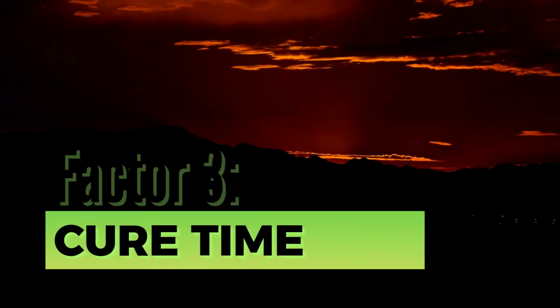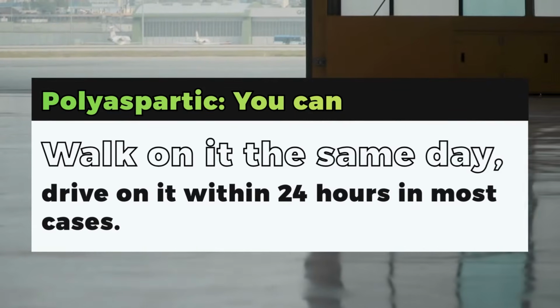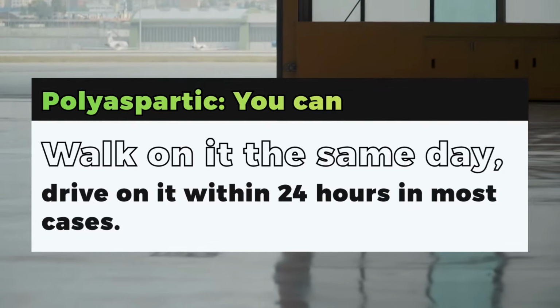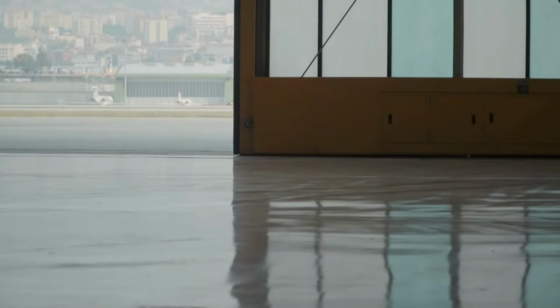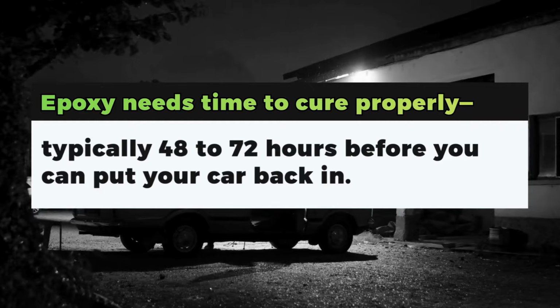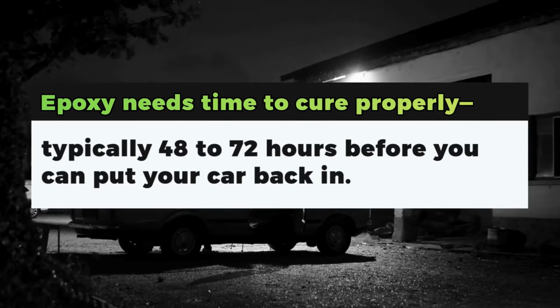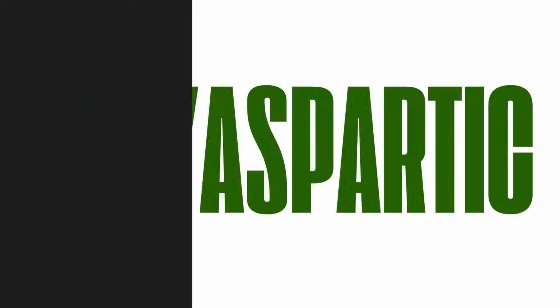Factor 3, cure time. Polyaspartic wins on the speed here. You can walk on polyaspartic the same day, and drive on it within 24 hours in most cases. But here's the trade-off, and this part can't be ignored. Epoxy needs time to cure properly, typically 48 to 72 hours before you can put your car back in. But that slower cure actually allows for deeper wicking and better bonding. So yes, the cure time winner is polyaspartic for speed, but there is a bonding trade-off.